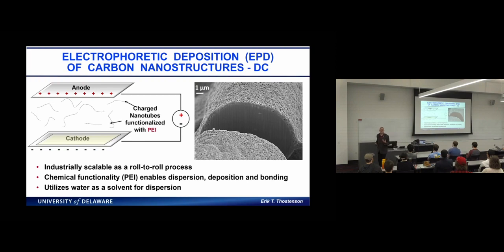We've studied a lot of different chemical functionalities, but we use what's called polyethylene amine. When we lower the pH, the amine groups protonate, and that does a couple of things. It stabilizes the dispersion. These tend to like to stick together, so the positive charge repels each other. That also gives us mobility, and we can use an electric field to deposit.